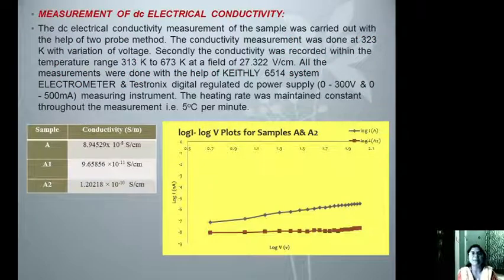Further, the sample was subjected to DC electrical conductivity measurement using the two-probe method. The conductivity was recorded at a constant temperature of 50 degrees Celsius while the voltage was varied. Similarly, the sample was subjected to a constant field of 27 volt per centimeter with temperature variation from 313 to 673 kelvin. At constant temperature, the VI characteristics of the sample are almost linear, and the room temperature conductivity of the three samples has been recorded here.